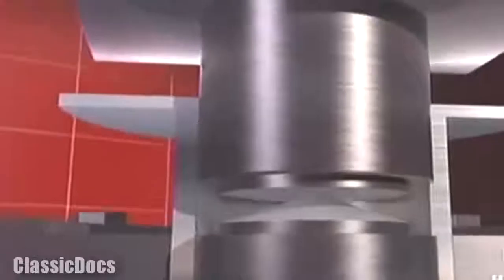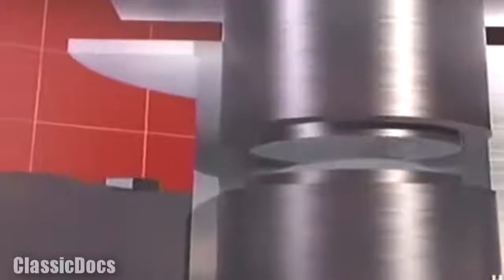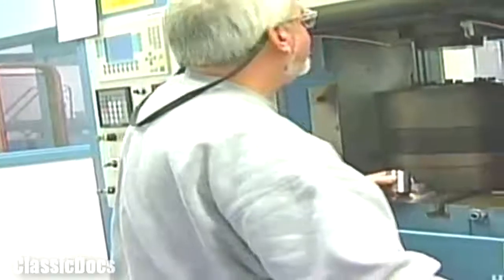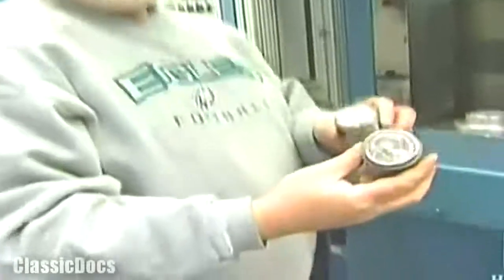In the die press, the reduction hub is positioned on top of a steel cylinder with a cone-shaped head. The two are precisely aligned with a centering ring. A press descends, flattening the cylinder against the hub. The cylinder's coned end prevents it from absorbing all the tonnage at one instant and allows its metal to flow in and around the hub's relief. The end result is a brand new master die.